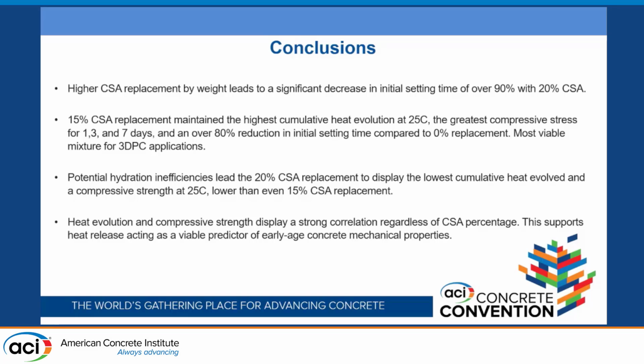It still has an over 80% reduction in initial setting time, and therefore acts as the most viable of all our specimens tested for 3D printable concrete applications. And we also saw that there's a potential for hydration inefficiencies which occur at higher levels of CSA replacement due to its consumption of possibly gypsum and other things, which we can see based on it having the lowest cumulative heat evolved at both temperature ranges and one of the lower compressive stresses compared to 15% CSA replacement.